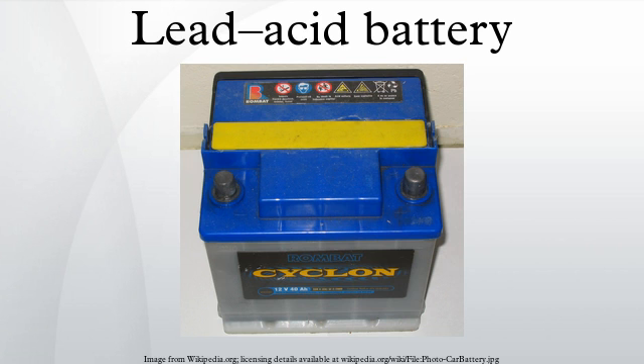Eventually so much of the battery plate area is unable to supply current that the battery capacity is greatly reduced. In addition, the sulfate portion is not returned to the electrolyte as sulfuric acid. It is believed that large crystals physically block the electrolyte from entering the pores of the plates. Sulfation can be avoided if the battery is fully recharged immediately after a discharge cycle. A white coating on the plates may be visible. Batteries that are sulfated show a high internal resistance and can deliver only a small fraction of normal discharge current. Sulfation also affects the charging cycle, resulting in longer charging times, less efficient and incomplete charging, and higher battery temperatures.